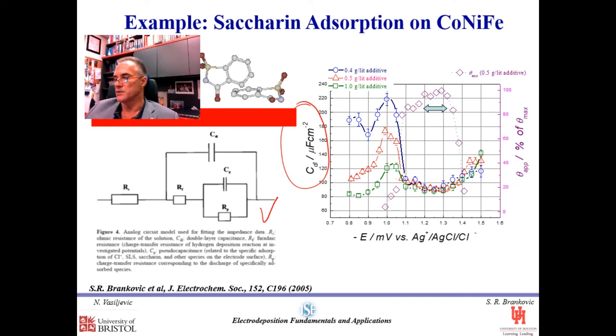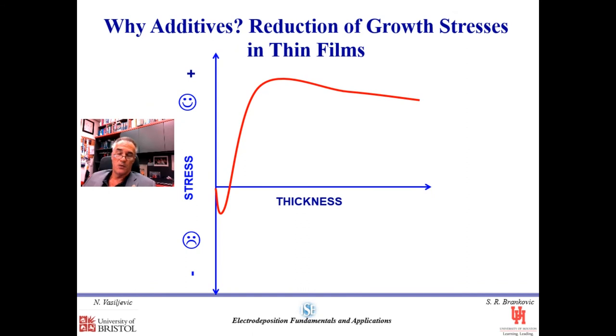electrode potential. And you can see, using the Frumkin relation for the coverage of the organic material as a function of the double layer capacitance, that the maximum coverage is somewhere between minus 1.2 and minus 1.3 volts with respect to the silver chloride electrode. So obviously the most effective action of the saccharin for this particular material, which is cobalt nickel iron, is in this potential regime. Now, why is that important?